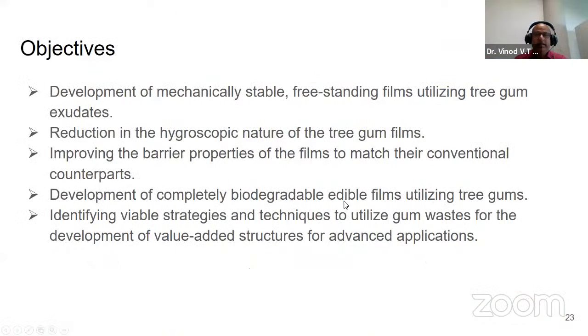The main objective is to develop a mechanically stable and freestanding film utilizing these tree gums, which are very important. We have reduced the hygroscopic nature of the tree gum by interaction with other materials, like other biodegradable materials or nanoparticle material, with the tree gums. The resultant material also shows high barrier and mechanical properties. And after the incorporation of nanoparticles or other additives like graphene oxide, these composite films also show biodegradation.